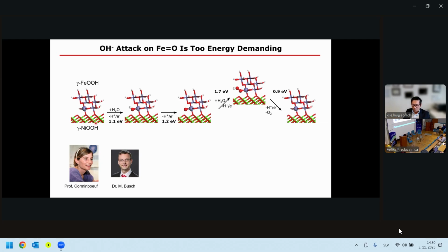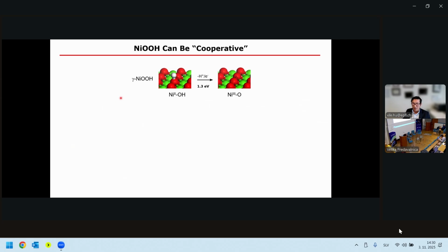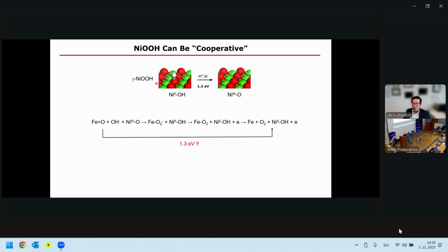However, in our case, we have a support on nickel OOH, and this is interesting because a lot of people already know nickel 2 to nickel 3 on nickel OOH is really facile. You can see by electrochemistry, this is about 1.3 eV, okay? So this cycle is quite readily accessible. In this case, we think you have cooperative catalysis where hydroxide first attacks the iron oxo. This is very difficult, but it does not need to make a bond, because the hydrogen here will be directly transferred to the nickel 3 oxo species as a hydrogen atom transfer. So in one step, you do it together. You make an iron oxo O2 species and nickel 2 hydroxide. The decomposition to make the iron catalyst again, plus oxygen and electron out, is really easy. Overall, according to calculation, it is again a really low energy at 1.3 eV.